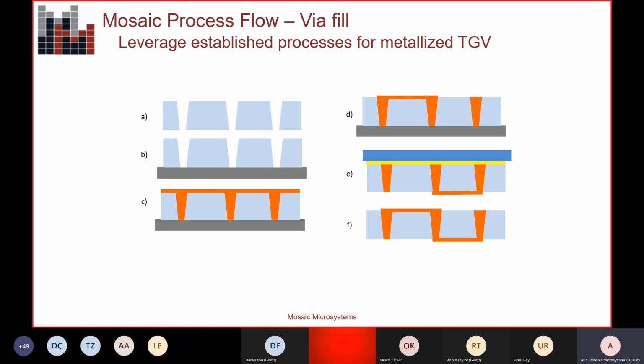For hourglass, people have tried conformal coating. That's good enough for some applications, but then you can't do a stacked via. People don't like an open via, so they want a fully filled via. If you need a fully filled hourglass, you're really limited to a 3-to-1 aspect ratio or smaller, and you tend to want smaller vias. So that gives pretty rigid design rules.